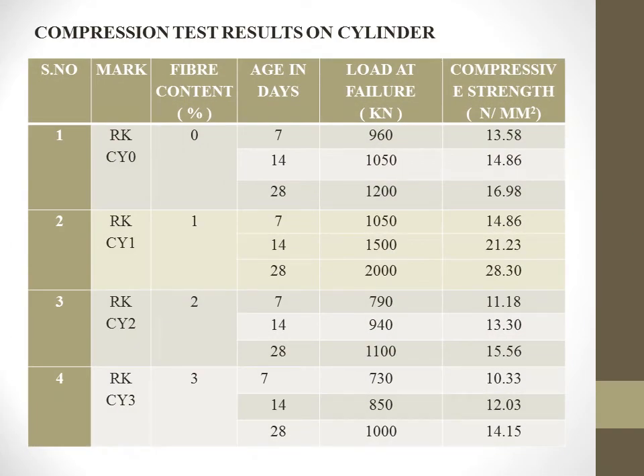And then we had also casted cylinders. We had put those cylinder specimens to compression strength test, and as you can see, with 0% fiber content, that is the nominal mixed concrete, the compressive strength was found to be 16.98, and with 1% addition of bamboo fiber, it has increased drastically to 28.3 Newton per mm square. And then, as usual, there is a gradual decrease with the increase in the fiber content.